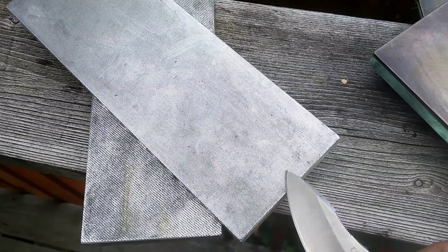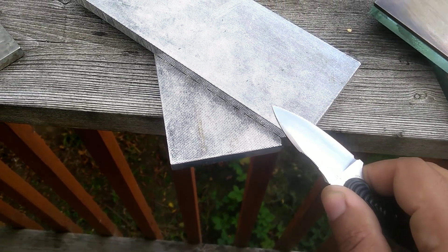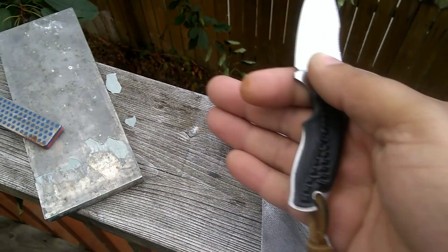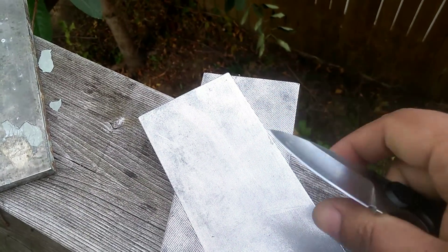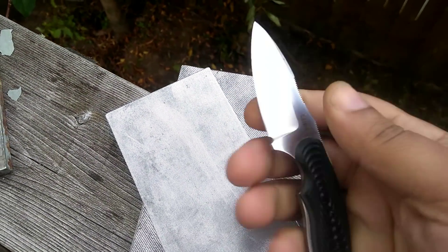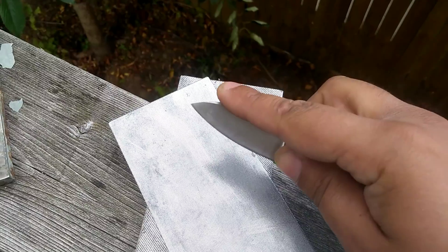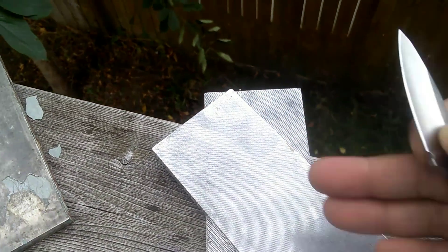The idea with the Atomas is that they have these little dots, and each of these individual dots is a cluster of diamond adhered to this plate. These plates are actually removable — you can buy the plate with the base or buy replacement plates — but the replacement plates are just as expensive as the ones with the base. Another disadvantage to these coated diamond abrasives is that because that grain is poking up and not bonded to anything, it's allowed to fully penetrate into the bevel. It gives a very deep, aggressive cut. Some people like that for very aggressive saw-blade-type edges and really high carbide volume steels. But it has a disadvantage: if you're going to higher grit or looking for a more refined apex, these deep scratches set you back — way back. You have to spend more time on another stone to clean out those scratches.